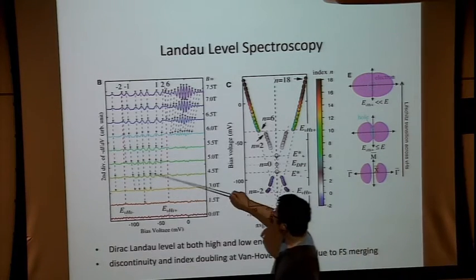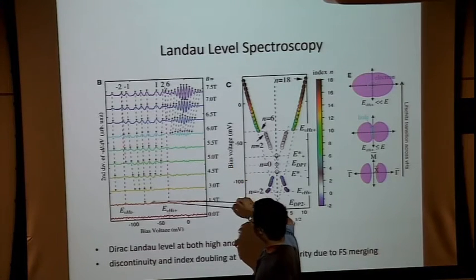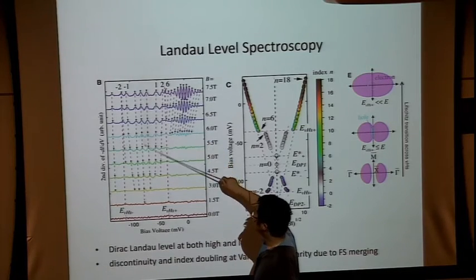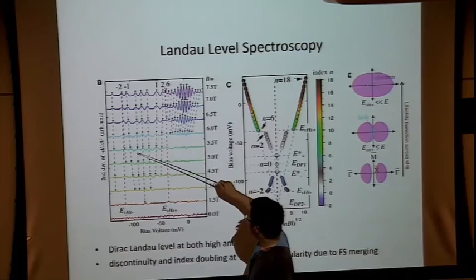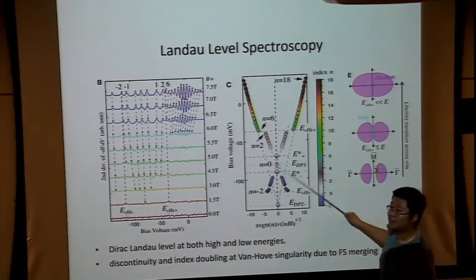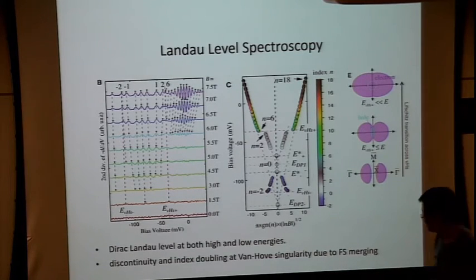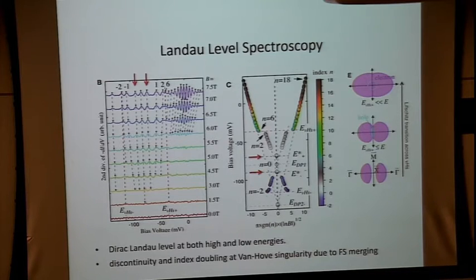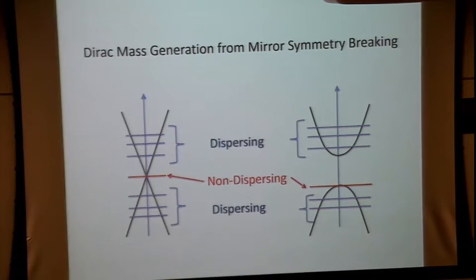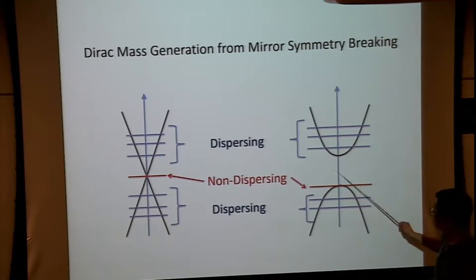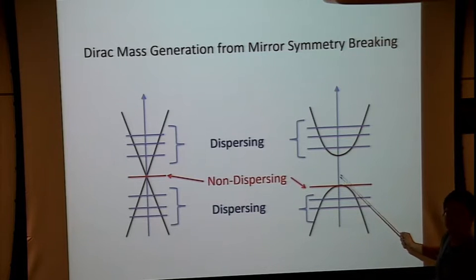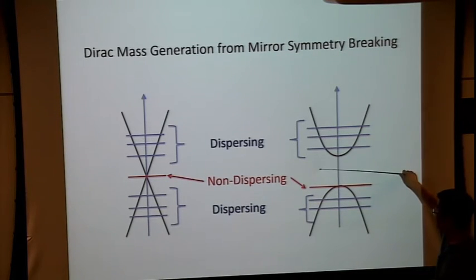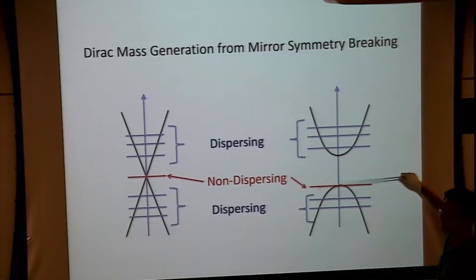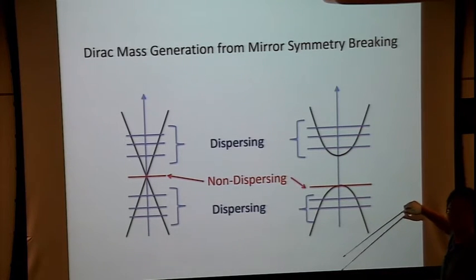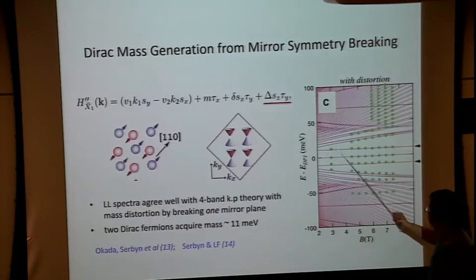I won't go into the details, but one thing I want to point out is that a particular feature is that there is one Landau level whose energy is independent of the magnetic field right at the Dirac point. That's what we expect from graphene's special zero energy Landau level. But there are two additional Landau levels on both sides of the Dirac point whose energy are also independent of magnetic field. So this was initially a puzzle, and then we realized this is exactly what we expect for a massive Dirac fermion due to structural distortion. If we have structural distortion, Dirac fermions open up a gap, but the Dirac mass at k and minus k has to be opposite. So when Dirac fermions have a mass, the zero energy Landau level is shifted either to the valence band top or the conduction band bottom, depending on the sign of the Dirac mass, but this is still independent of the magnetic field. So this explains the three peaks that are independent of field.